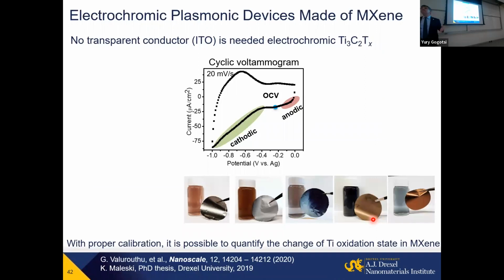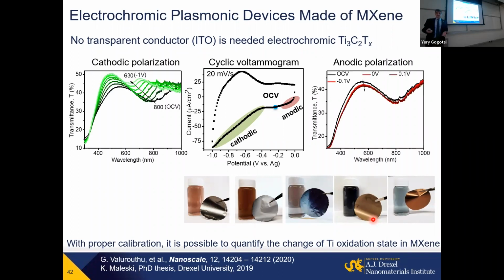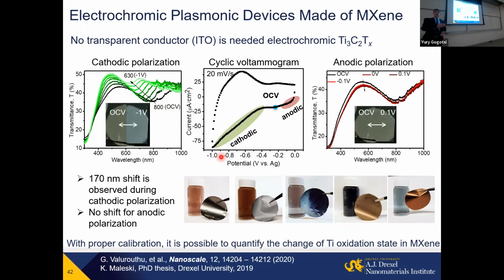Or you can actually combine different properties, and you can make an electrochromic plasmonic device, where you can have a shift of, like in this case, Ti3C2, just with 1 volt, 170 nanometers. So you can go basically from green to blue with 1 volt applied. But moreover, it's not a conventional electrochromic device where you change the state. It's actually you shift a plasmon resonance, the surface transverse plasmon peak, which only depends on the thickness and the electronic properties of the material. You change it here.